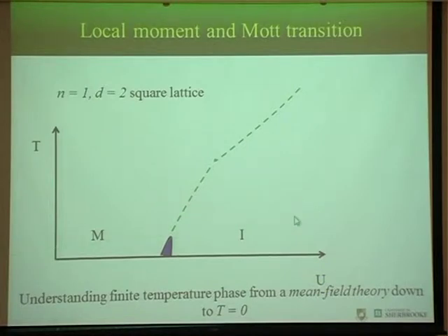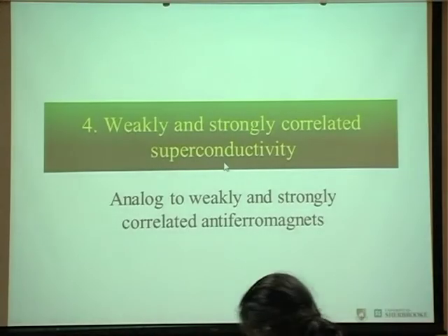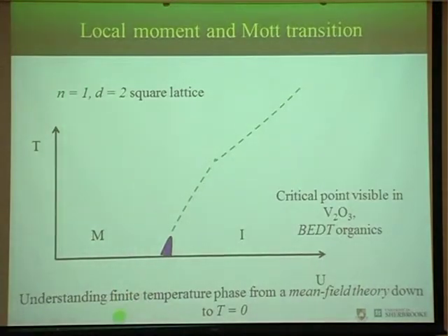If you remove the antiferromagnetism and try to describe what happens to this line by a mean field theory all the way to zero temperature, what you find is a first-order transition that ends at a critical point. In fact, this critical point is seen in V2O3 and the BEDT organics, but in many cases it is just not seen, since antiferromagnetism goes above it. But the crossovers are seen.